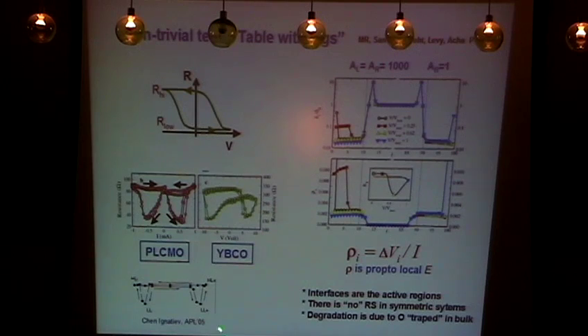So this is the resistance versus voltage that you get along different applications of a pulse protocol, and when you do that in a systematic manner to get the hysteresis loop response, you get exactly that: this system has this table with legs in which the loop becomes very non-trivial. So it goes up, down, recuperates there, goes down, and up again. And this is independent of the system. This is PCMO, and this is YBCO, two famous transition metal oxides. These are the colossal magnetoresistance, and this is the cuprate.